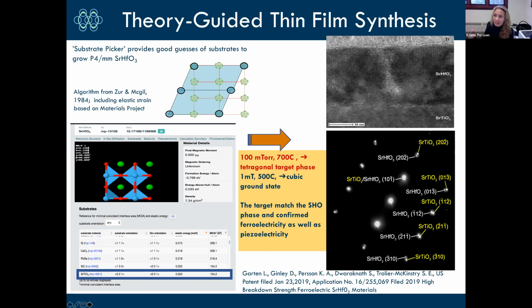If you grow it thicker, it actually transforms, so it is definitely metastable. But it was confirmed ferroelectric as well as piezoelectric, with a fairly high breakdown strength in the thin film form.